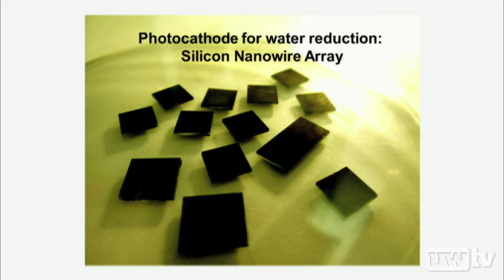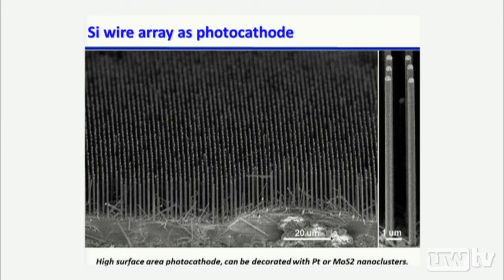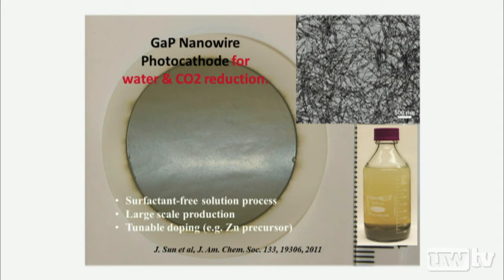If you are thinking about CO2 reduction, as I mentioned, the conduction band edge needs to be more negative because the CO2 reduction half reaction is much more negative compared to water reduction. One of the good materials in terms of having the right conduction band edge is gallium phosphide. For this purpose, we developed a very simple surfactant-free colloid process to make these gallium phosphide nanowires. We can make all these high surface area structures in solution now, a very low-cost methodology, for both water reduction and CO2 reduction.